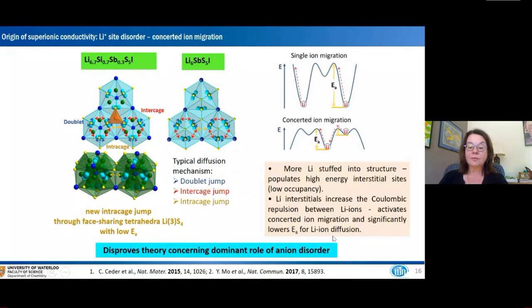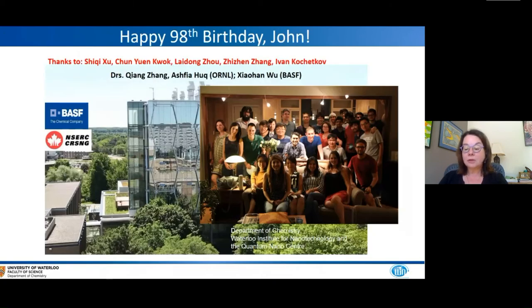And so Yifei Mo has shown that when you stuff lithium into a structure, you effectively populate these high energy sites, and that activates concerted ion migration, lowering the activation energy for diffusion. We believe that this is the mechanism responsible for our conductivities of upwards of 15 to 20 millisiemens per centimeter. So I'll just end off.